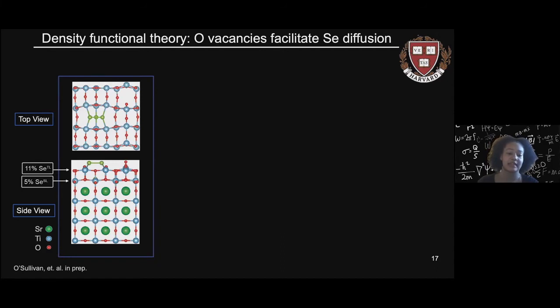After presenting our experimental findings, I'll now employ density functional theory to provide more evidence that oxygen vacancies can facilitate the selenium diffusion into the strontium titanate bulk. So what I present to you here is a top view and side view of our strontium titanate and monolayer iron